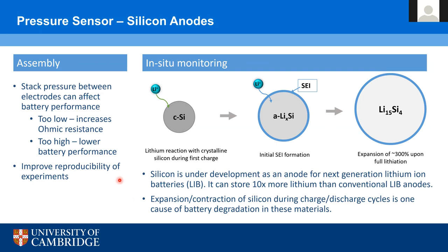The first is when we assemble the cell. The stack pressure, the pressure applied between the anode and the cathode, is quite important, because if it's too low, then we introduce extra ohmic resistance, and if it's too high, then we reduce the battery performance. So it's really key to get an optimum pressure between the two electrodes, and we think this is dependent on the battery chemistry used as well.